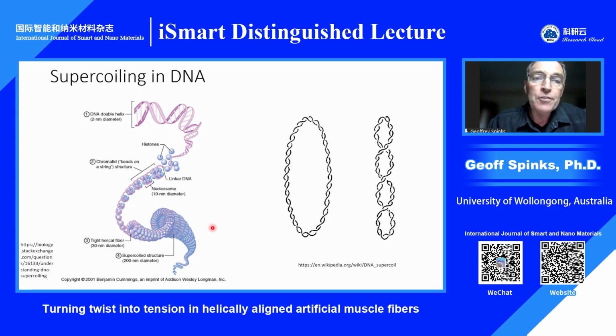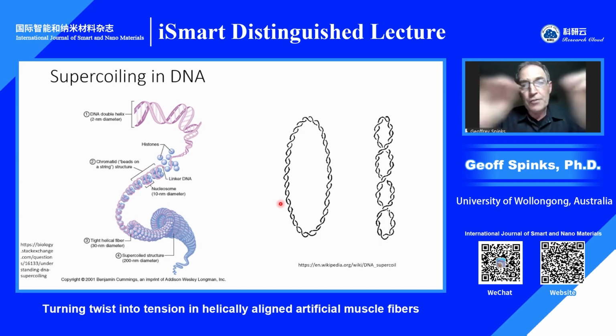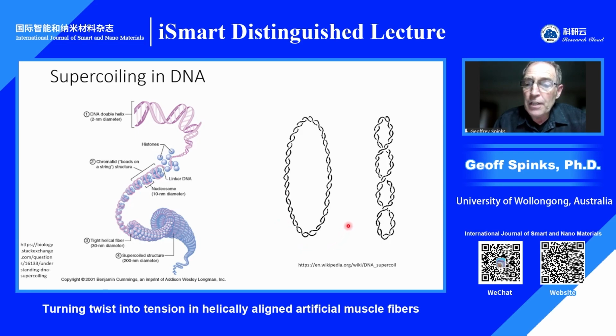But what's really interesting is that DNA does not supercoil by inserting twist. You know, there's no mechanism in nature that grabs the end of the DNA molecule and starts twisting it. No, it's supercoiled by the action of chemical agents or active species like histones and other proteins. So it's basically a physicochemical process that causes the DNA fiber to supercoil. Another example of DNA supercoil is that DNA exists in nature as a closed loop rather than an open strand. And very often, these closed loops are observed as plectoneme type structures, which, as I demonstrated earlier, is another example of supercoiling.